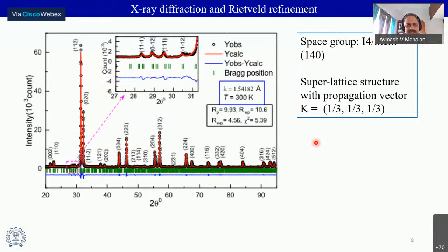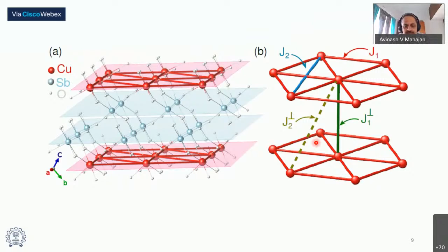Okay, so one establishes that there is a Cu-Sb site ordering, and in that case, as I showed in the earlier figure, the 1-1-1 planes harbor the triangular geometry. Now, if you look at the bulk properties, which we come to shortly, so this is again a caricature of the triangular planes.